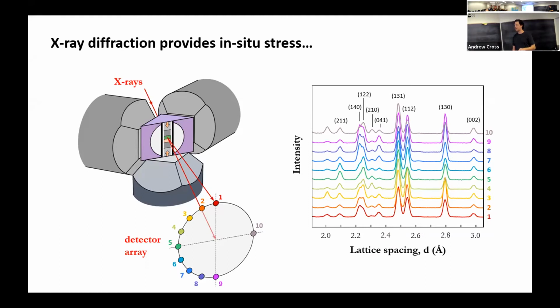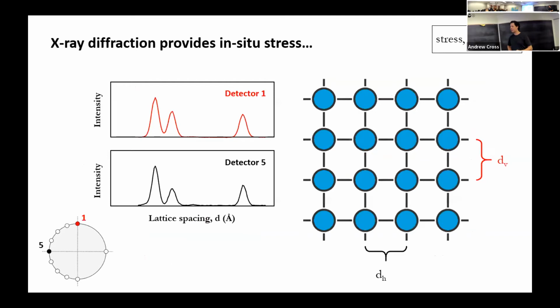The peaks here correspond to specific crystal lattice planes in our aggregate. This is a pattern for olivine, the forsterite. And the positions of these peaks tell us something about the lattice spacing, how closely those crystal planes are spaced apart through an experiment. And we can use this to calculate some sort of in situ stress.